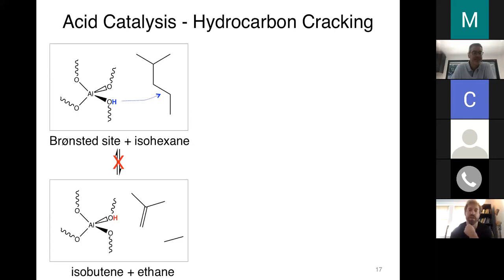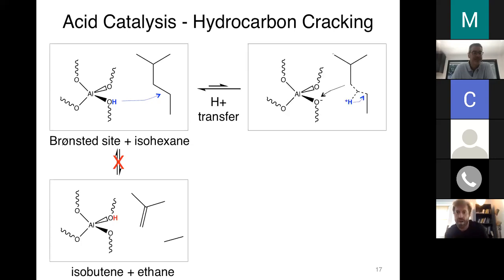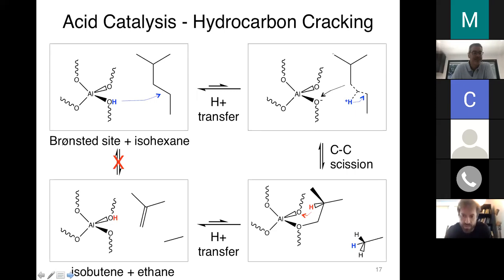So in the first step of this reaction, you have this very acidic proton attacking the carbon-carbon bond in the substrate, forming this carbonium ion pair. And in a subsequent step, the carbon that's indicated with an arrow is going to rebound on the negatively charged oxygen, forming a grafted oxygen-carbon bond and releasing ethane. And then finally, in the last step of the reaction, the proton on the substrate is going to rebound on the aluminum T site, releasing isobutene. So in this case, the aluminum T site, you could think of it as a shuttle, allowing for protons to be removed and placed in precise positions on the substrate, enabling this reaction to occur.